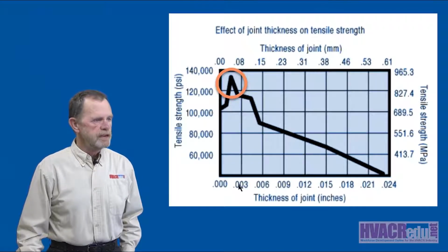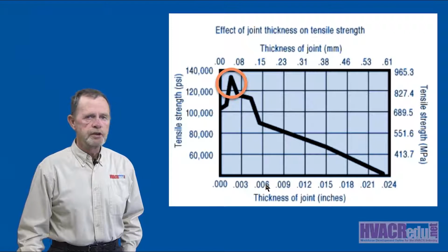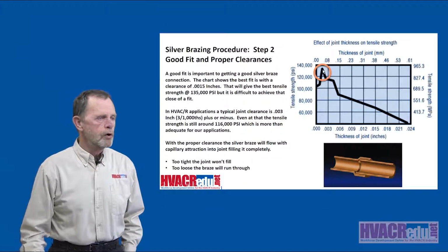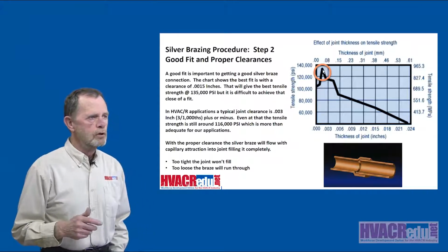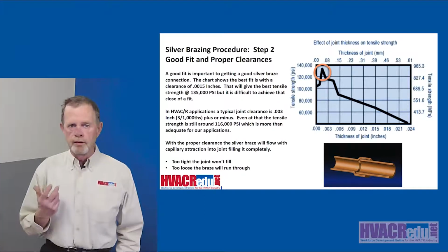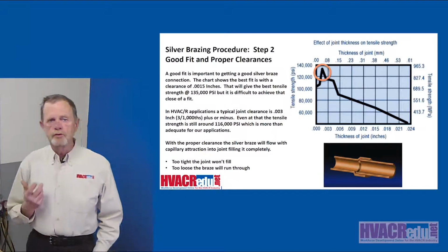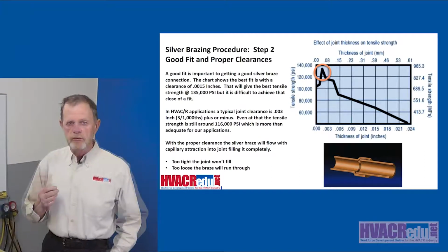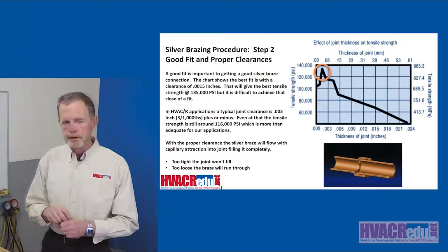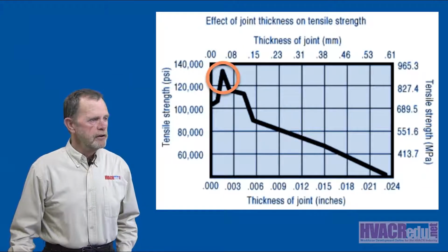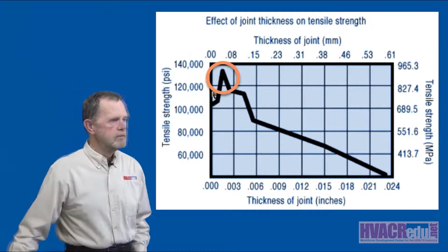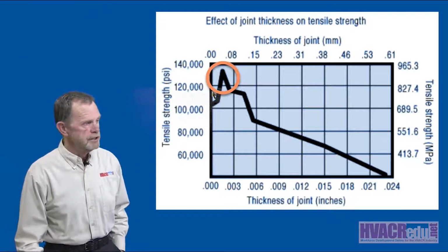But then, as you can see, as the fit gets looser, so to speak, it drops down and drops down and drops down. Generally speaking, your swaging tool will give you, or if you're using already made fittings, you'll usually get at least about a 3/1000th of an inch fit between the pipe and the fitting. So as you can see down here on this chart, if I'm at 3/1000ths of an inch on my fitting, then I'm going to get about 116,000 psi tensile strength, which is plenty.